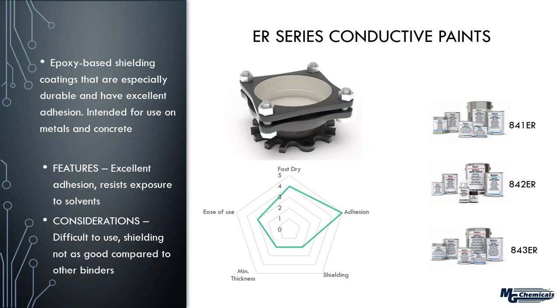Next, we're going to look at a more recent series, the ER, or epoxy resin conductive paints. Now, epoxy typically invokes for a lot of people the idea of a heavy duty material. That's because they hold up very well to physical as well as chemical abuse. So these in general you can classify as having excellent adhesion to a very wide variety of substrates. These include concrete, masonry, metallic type substrates, but they also survive very harsh environments that other binder systems don't. So for example, if it has exposure to fuel vapors, chemicals, solvents, that sort of thing, epoxy stands out as the product that you want to consider. And we have three different products to address those needs.